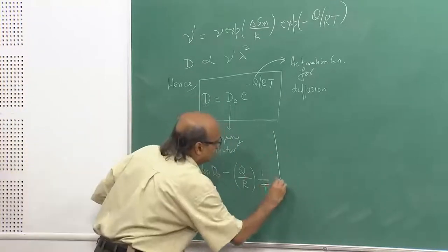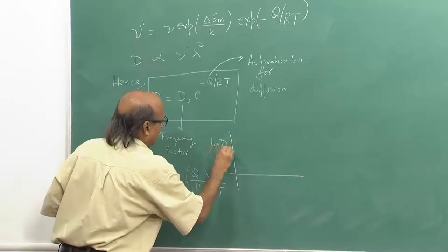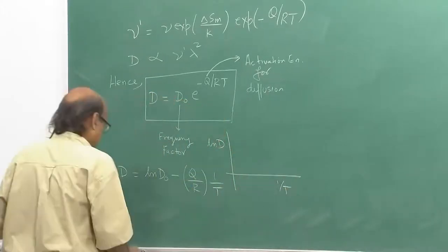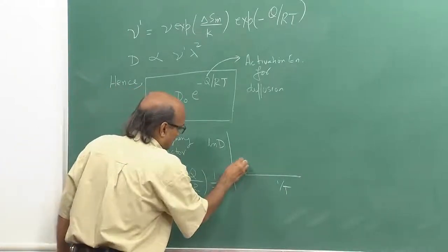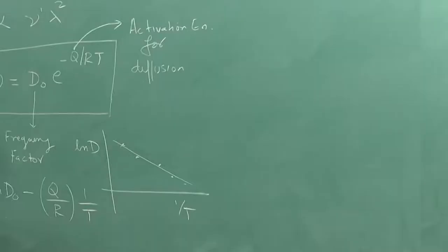And if I plot log D versus 1 upon T and I put in the data points I get for different temperatures, they should fall on a straight line. So, I put a best fit line through this, and from the slope and the intercept I can get the values for activation energy and D0, and after that I can get D values for other temperatures.